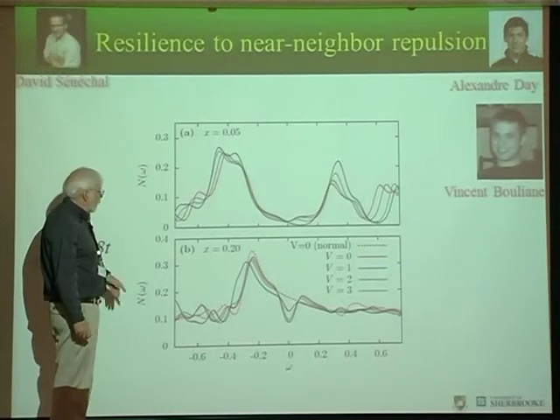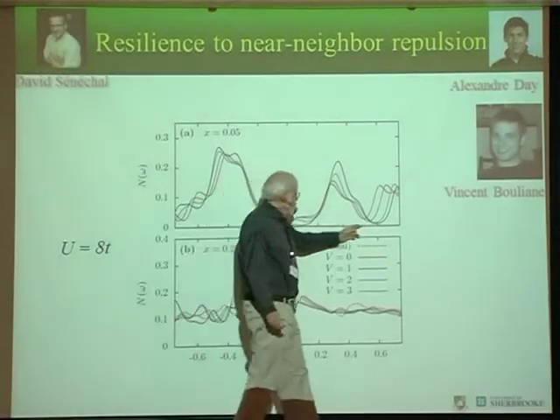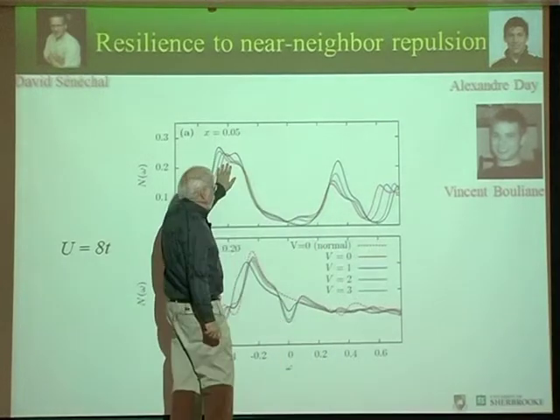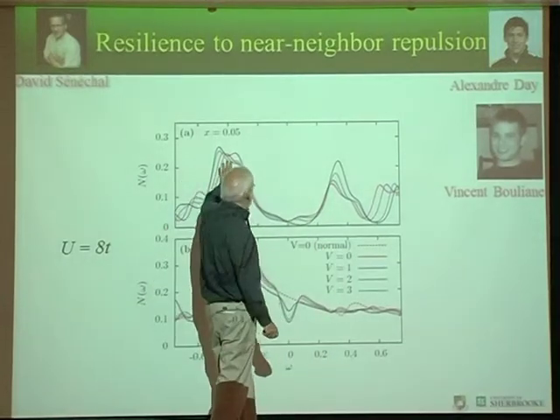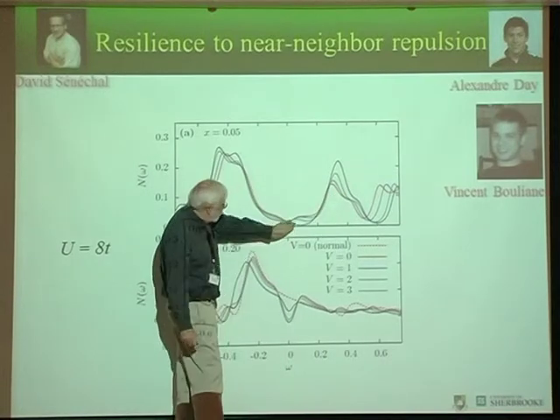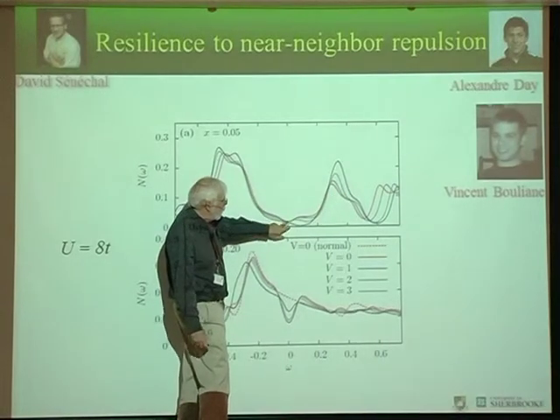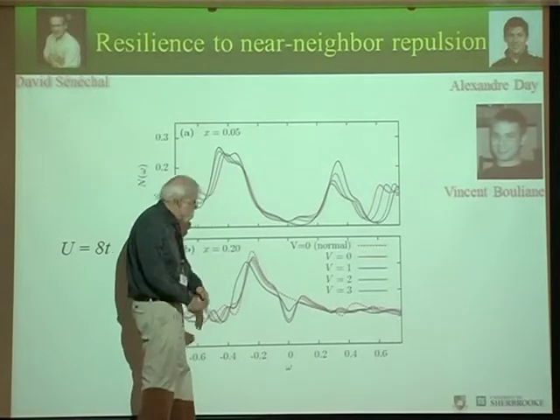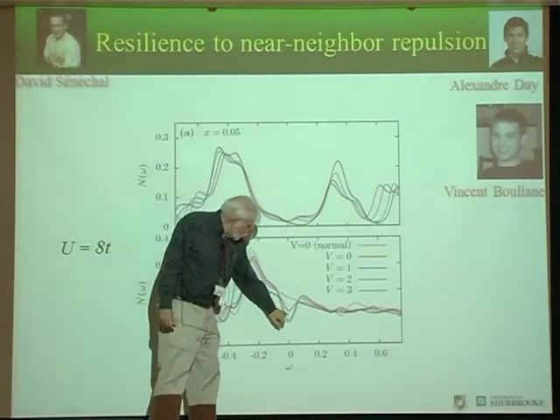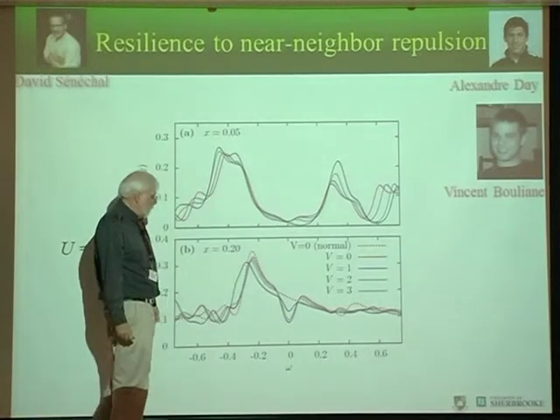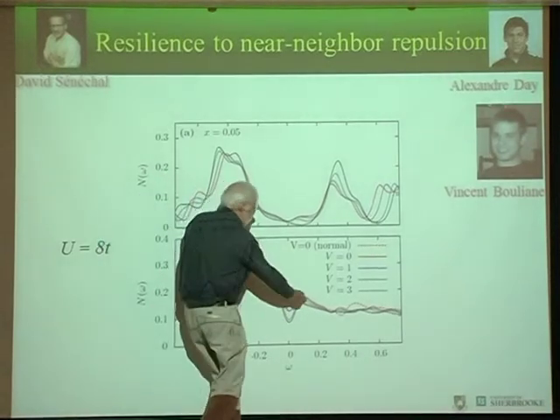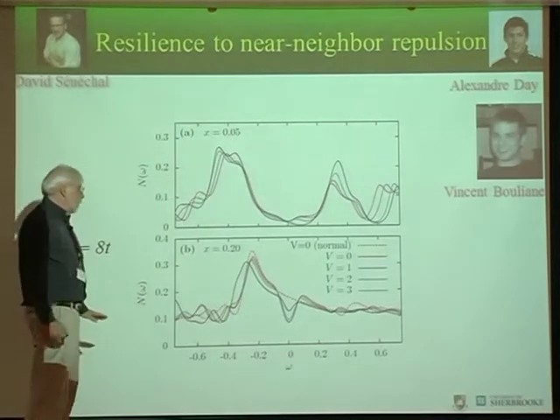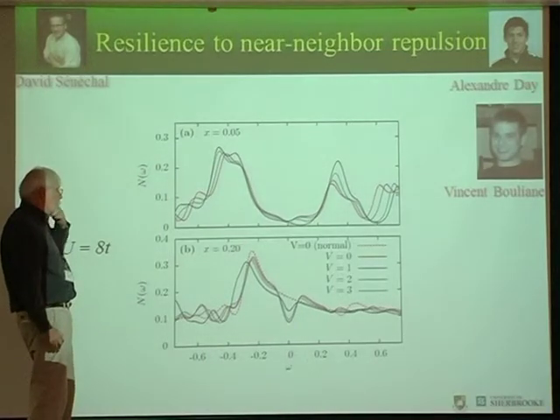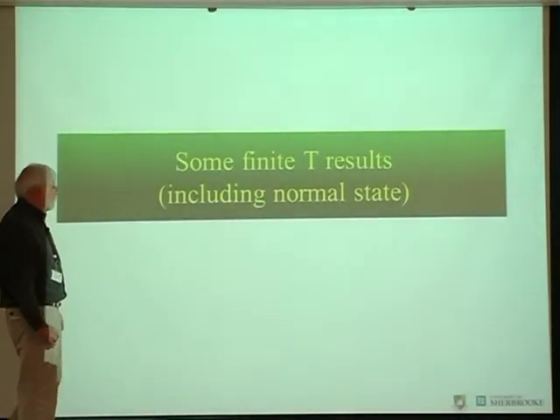If you look at the density of states as a function of frequency, this is the underdoped regime. You have the pseudogap, and you have this superconducting gap here that is much smaller and does not depend that much on V. In the overdoped regime, it depends more on V, and that's the superconducting gap, and that's the pseudogap. You see this asymmetry between electrons and holes here that is very important. Okay, so now I have to skip all of this.